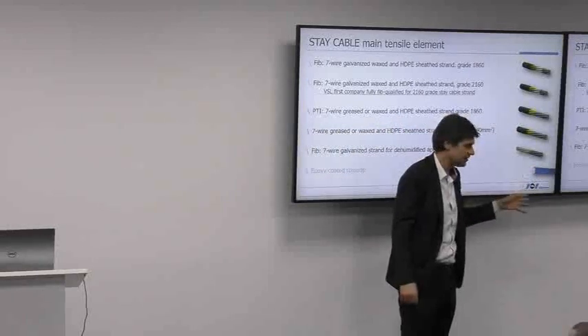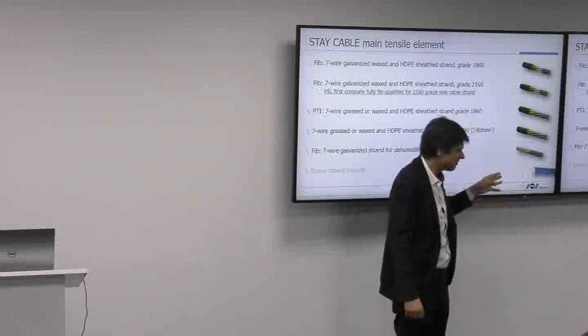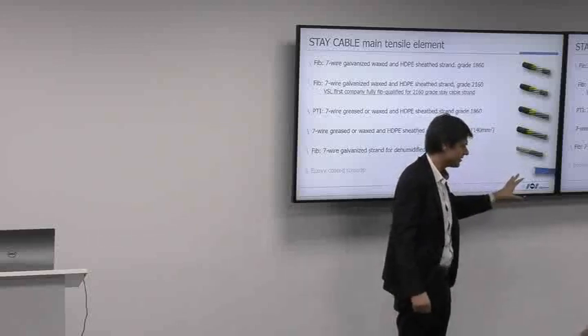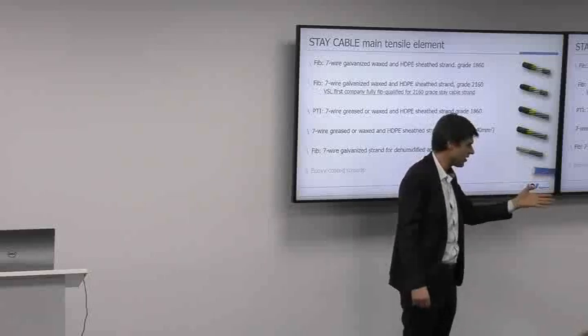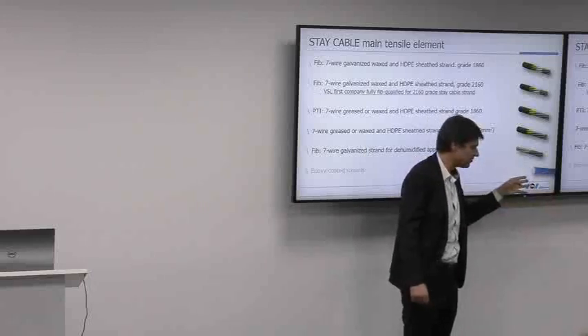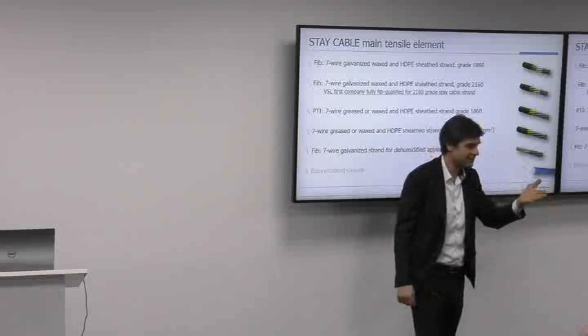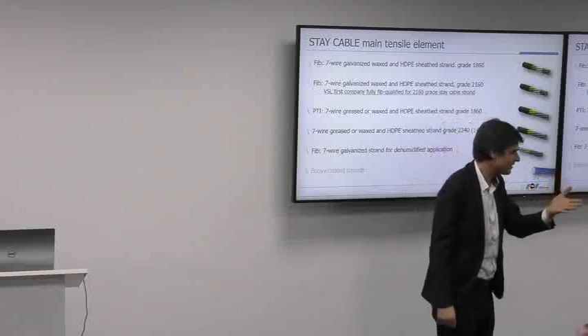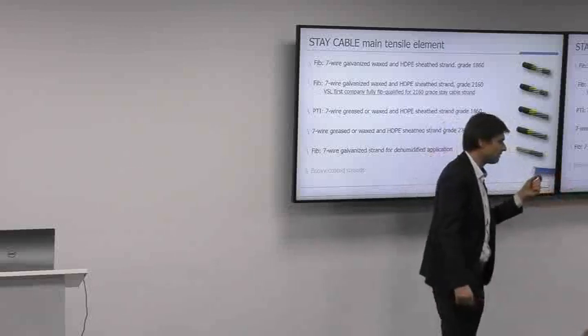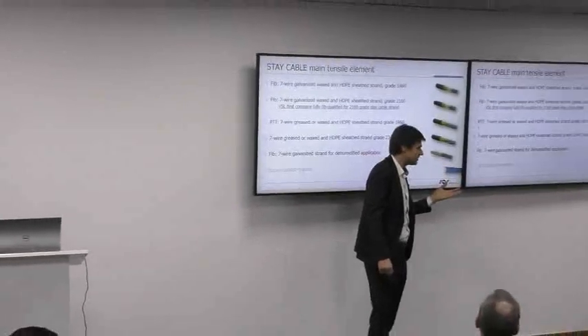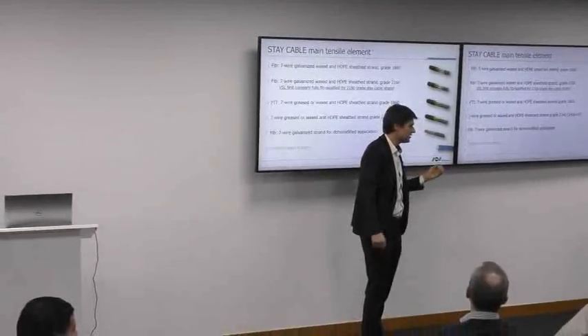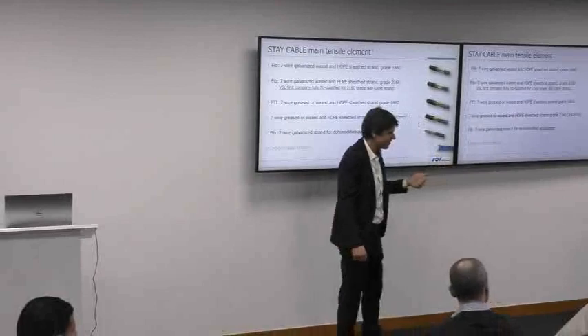Do you have epoxy-coated strands for stays as well? We have experience, but we will never recommend this technology of strand. Maybe we can discuss this. Why we do not recommend this? Does it crack? Sorry? Crack. Yes, correct. It's getting very cracked. Famous on internal strands, but then you have a lot of wedge loss, et cetera, right? You have a huge setting of wedge, and you have a huge increase in relaxation.